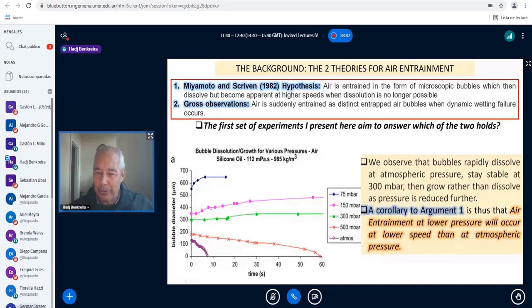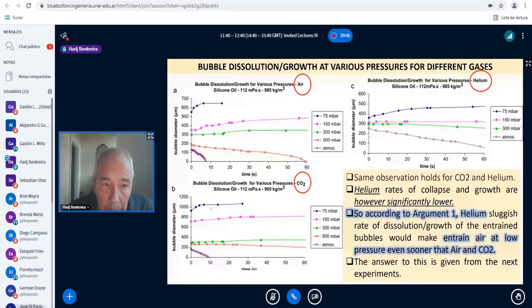So a corollary to this argument is that air entrainment at lower pressure should occur at lower speed than at atmospheric pressure, because the gas is not dissolving. Okay, let's see if that is true. Then we did exactly the same experiment with CO2 and with helium, and again we saw exactly the same thing.